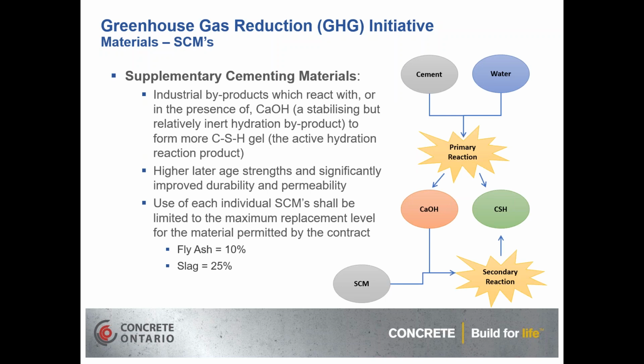Now, supplementary cementing materials, these are industrial byproducts from the iron industry, from the coal generation industry, where we're looking at slag or fly ash that they can't use. And instead of landfilling the material, we've found a use for it in our concrete. And what these materials do is they will react in the presence of calcium hydroxide. And when we look at the basic cement and water chemical reaction, and this is a simplification of it, when we mix cement and water, we're going to generate calcium silicate hydrate gel, which is the good stuff that gives our concrete the strength, the durability, it bonds everything together.